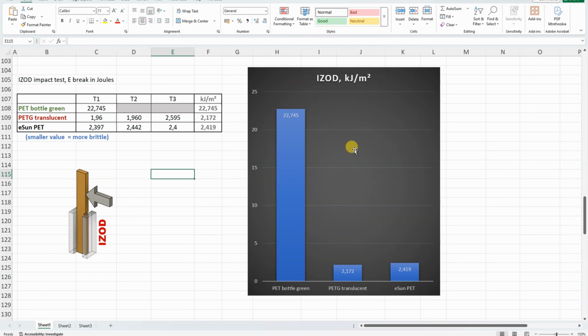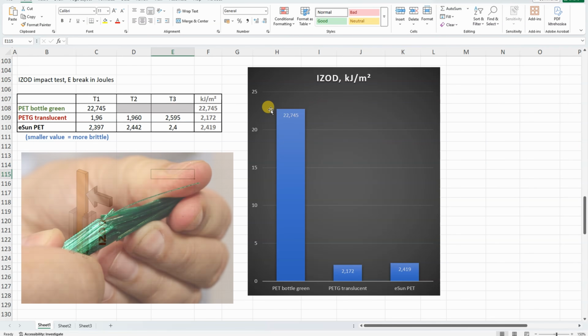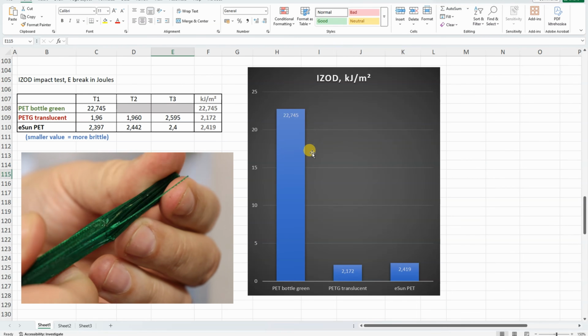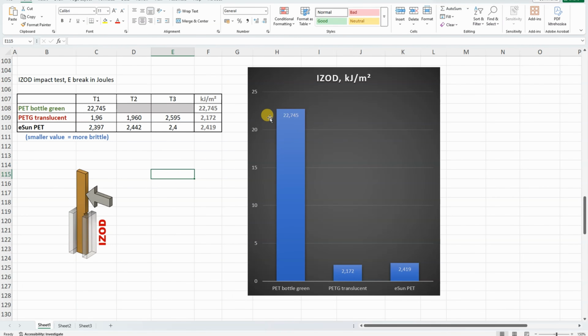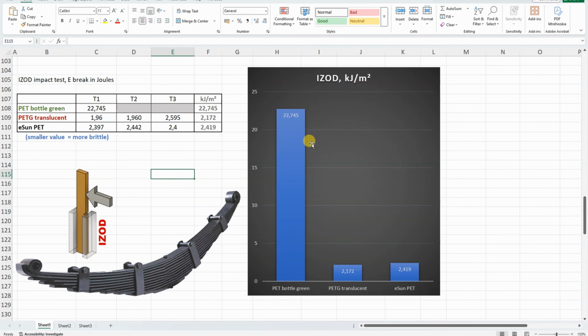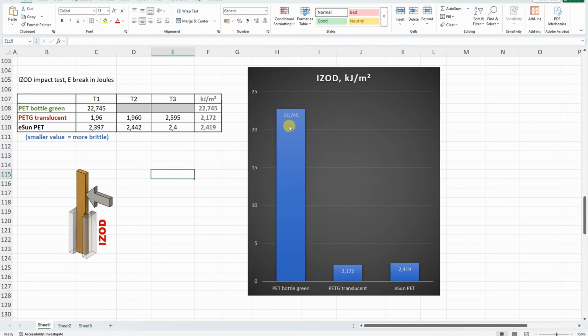But if you are following my channel, then you probably already know the reason for this, because I mentioned several times that when I find a material with a weaker layer adhesion, it usually performs well on the impact test. It is something like a leaf spring effect, and that's what we can see here.